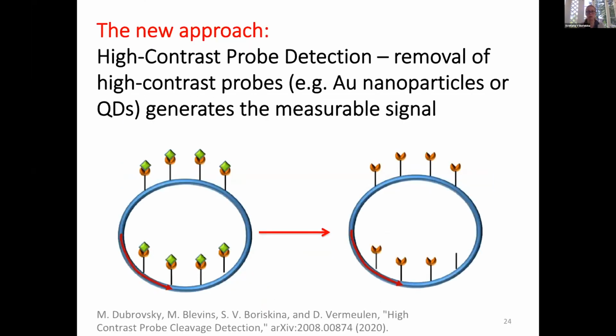So the new approach we're trying to pursue, we call it high contrast probe detection. We suggest to completely reverse the situation. Instead of trying to capture very little material that may or may not be present in the sample, we want to functionalize our sensor with some very high contrast probes. These probes could be metal nanoparticles or quantum dots, or something large enough and generating such a big optical signal that even if you remove just one of these probes, or especially if you remove many of them, you for sure will have a signal that's above the noise.